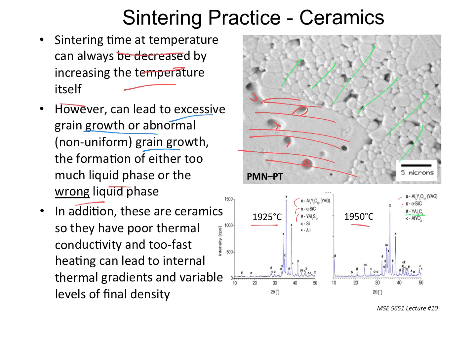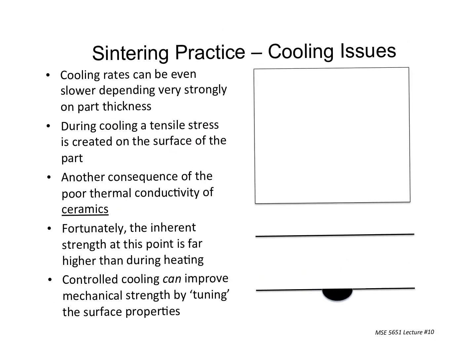Okay, let's see. And we also have cooling issues, which is one of the really annoying things, especially in some large parts, like a lot of these aerospace parts. You can have something that heats up, and you let it sit there and densify, and then you cool it down. Let's go back to those numbers. Say we're sintering at 1950 C, which is not out of the question, and we start to cool it down. So our furnace is now at a relatively chilly 1800 degrees centigrade, because we've shut the furnace off or started to ramp it down.